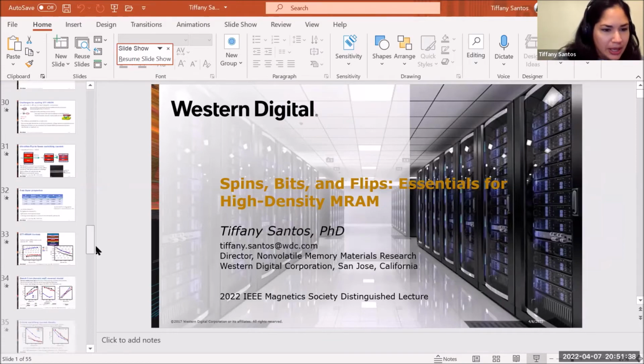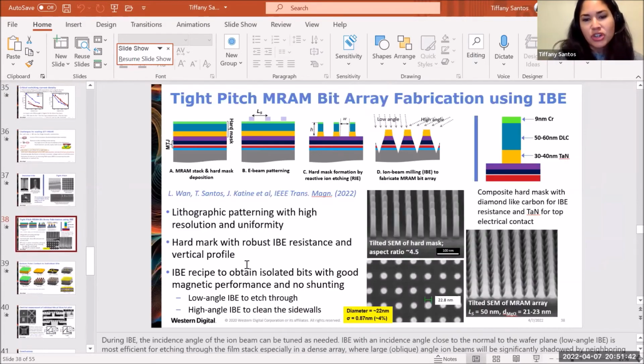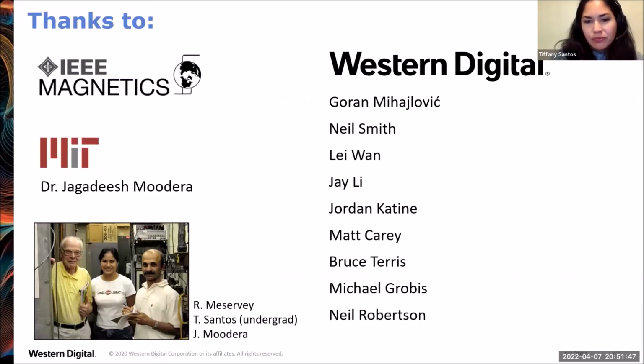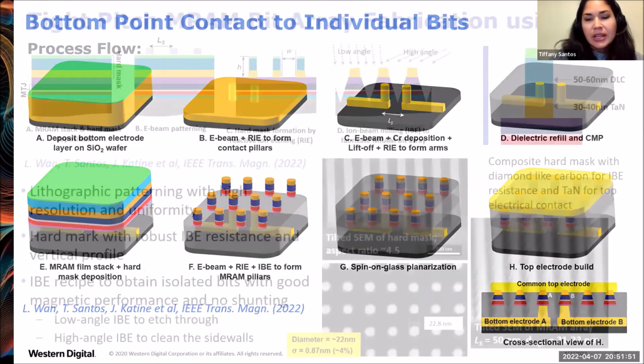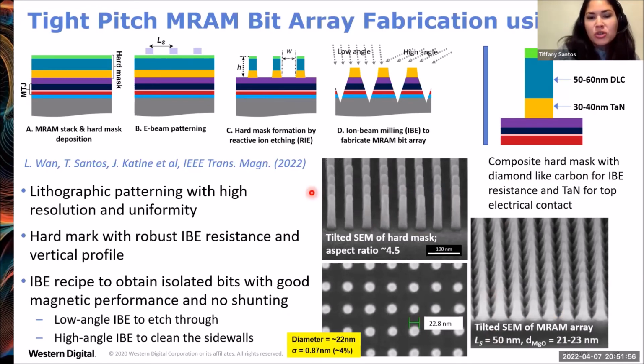Yes, this is something that adds a challenge to the process for sure. So really for the hard mask, what is important to achieve is this high aspect ratio with the vertical sidewalls. And then the milling process is this two-step process where the second step focuses on milling away the redeposited material on the sidewalls. In all of these etch steps, the substrate is rotating to get a uniform removal of material on all sides. So it's very close attention to the profile of the hard mask, and then figuring out how to tune this angle, and also for the pitch that you're trying to achieve.